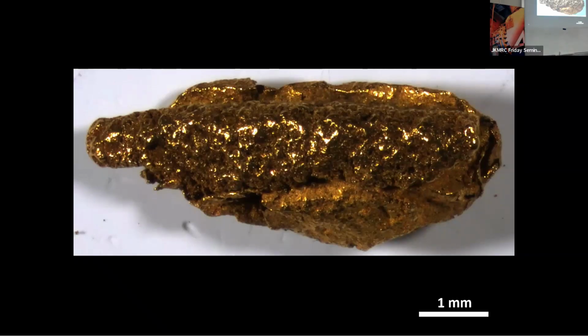And we'll have a little sodium hydroxide pellet to grab the CO2 so the lead carbonate doesn't form. But it's difficult to put lead into solution; a plumbogummite will precipitate, your lead carbonate will precipitate, and then you've got lead 2. Those salts could erode, but it's not going to behave the same as gold will. We've looked at colloids and crystals formed with silver, with platinum, with palladium, and it never seems as active as the gold in terms of the crystals. We seem to get colloids, and that's where it stalls.